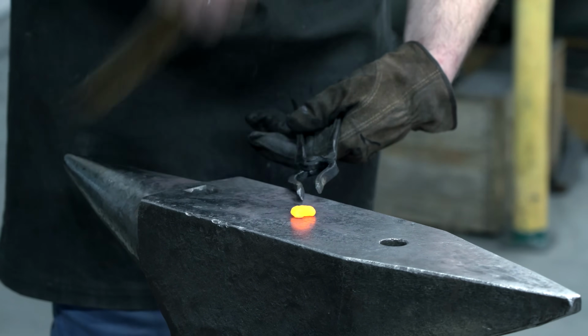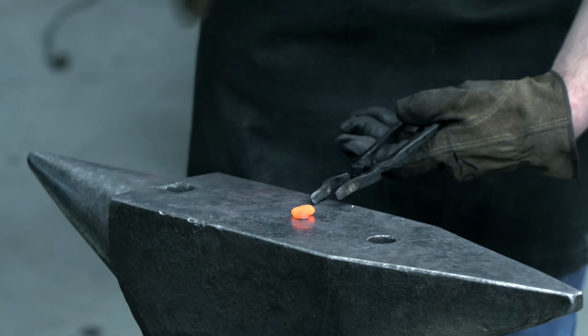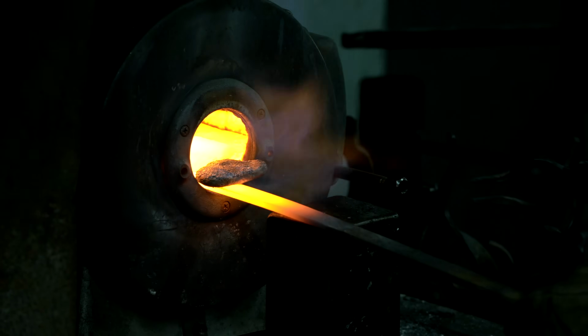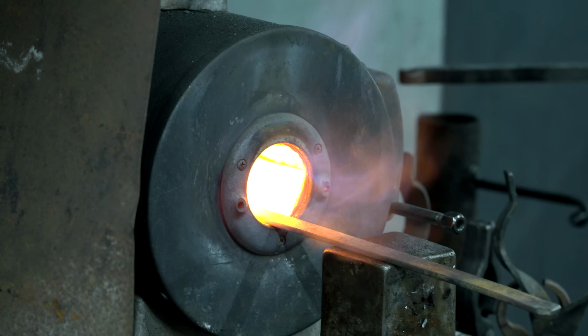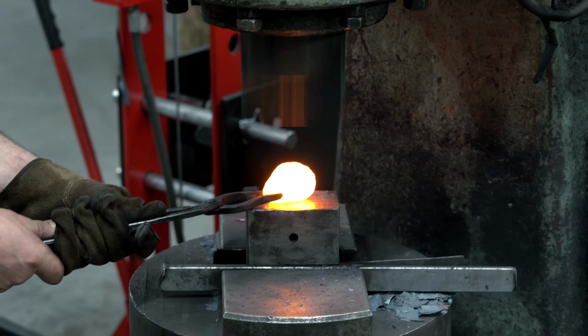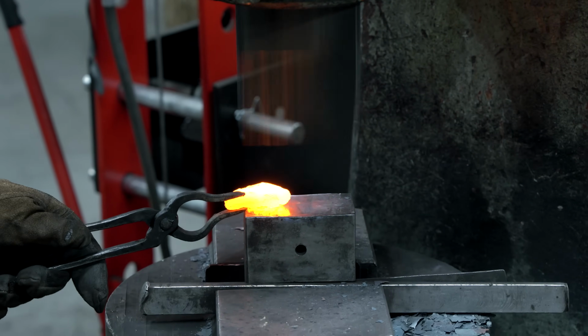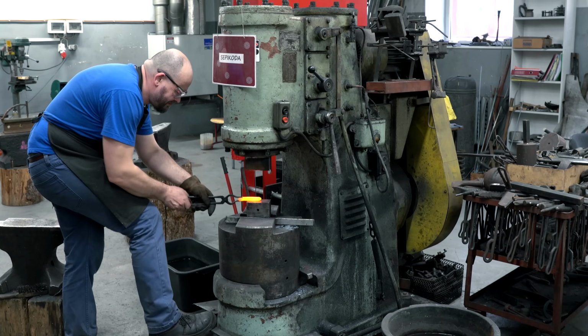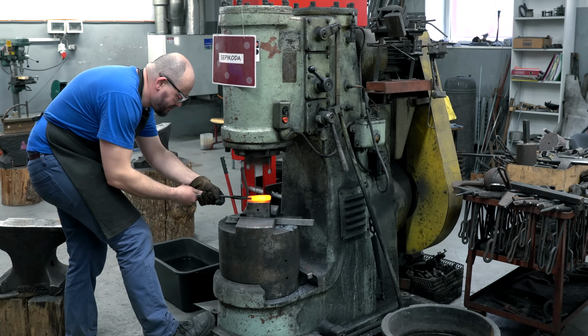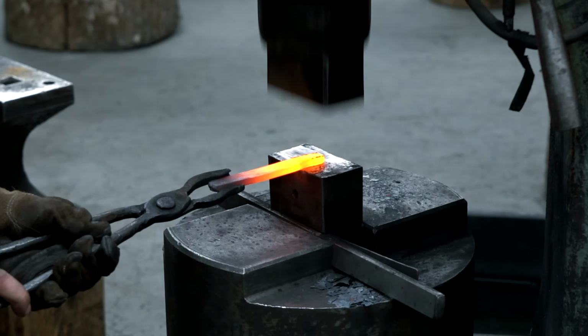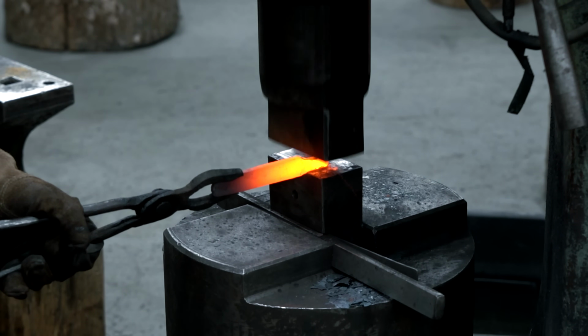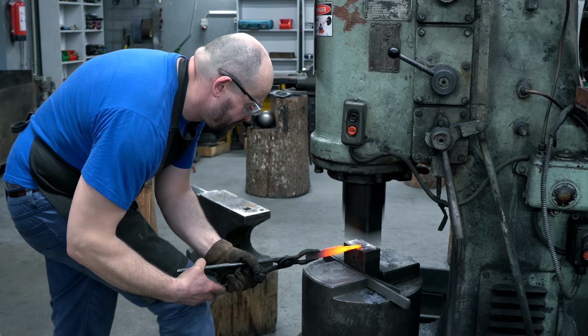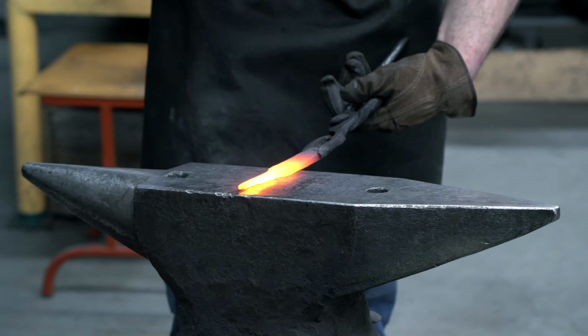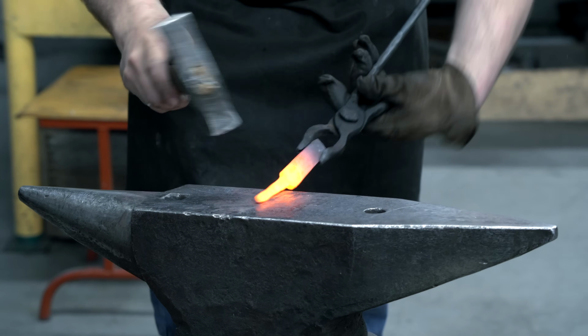To my delight, after the first hit with a hammer, the small nugget didn't crack, and according to the blacksmith, it forged quite easily, even though it retained some hardness, and was more resistant to forging than a regular soft steel. After the first successful test, we threw my small stainless steel nugget into the furnace, and after that, Edwards decisively began to forge the nugget into the needed shape, with the help of a large mechanized power hammer. It would take a whole day if we did it manually, but like that, this process takes a few minutes. More precise shaping needed to be done manually, which also took some time.